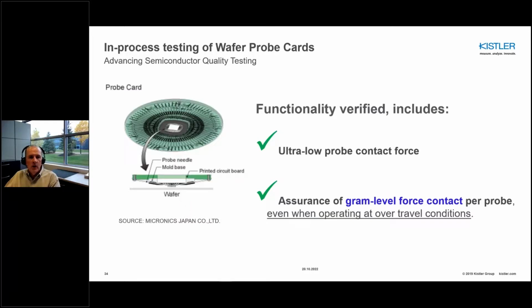It is well known that testing multiple chips on a wafer requires probe cards to be utilized. Again, the concern is not to damage the individual die contact points during the wafer testing. Here, manufacturers of wafer probe cards must also verify that ultra-low probe force is generated, even when the probe cards are being operated at over-travel positions. Now I'm approaching the end of this presentation, and we'll wrap up the key points on the next slide.